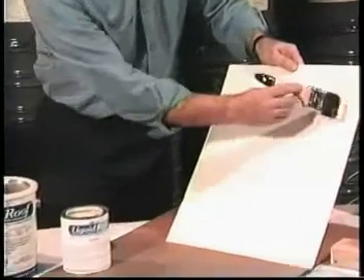If you're spreading Liquid Roof too thin, it will drag on the brush or roller and will either not self-level or require more than 10 minutes to level. If too thick, Liquid Roof offers little spreading resistance and the surface levels in about 1 minute. You have the right thickness when it's comfortable to spread with slow brush or roller strokes and takes 3 to 5 minutes to level.